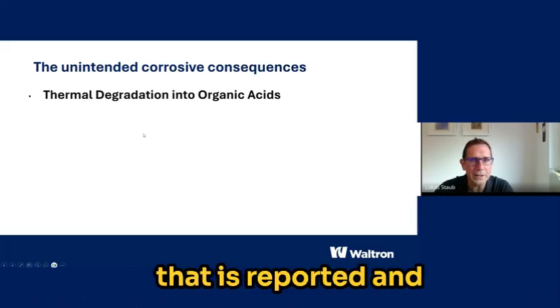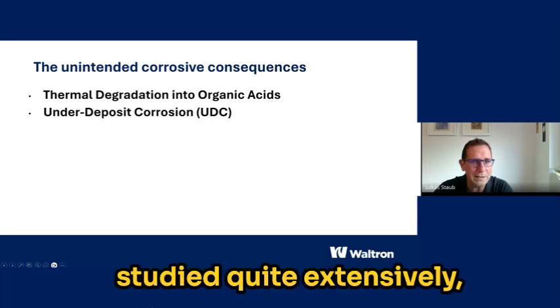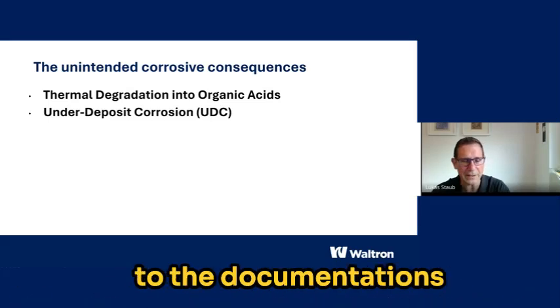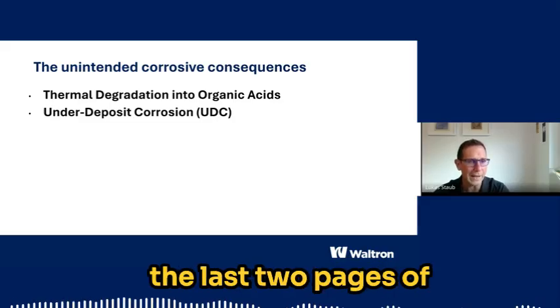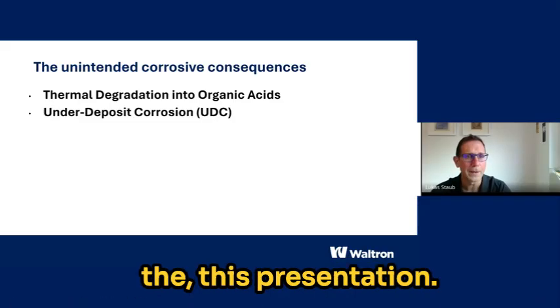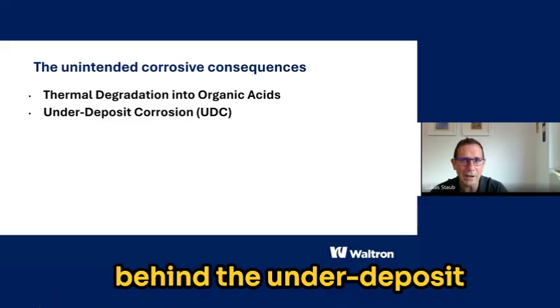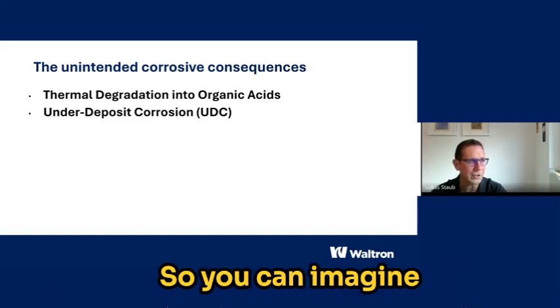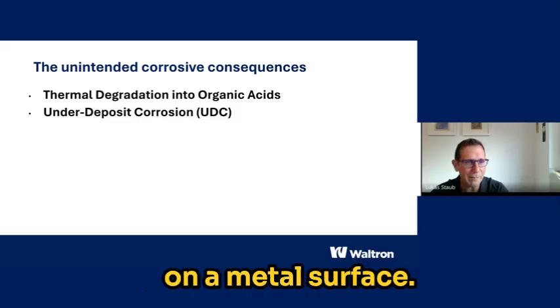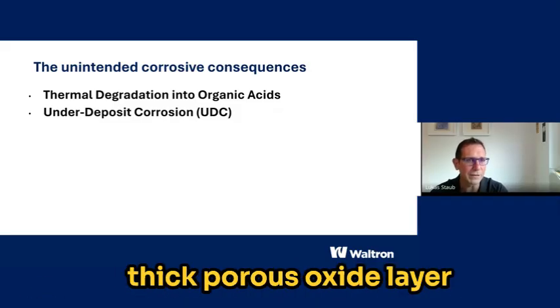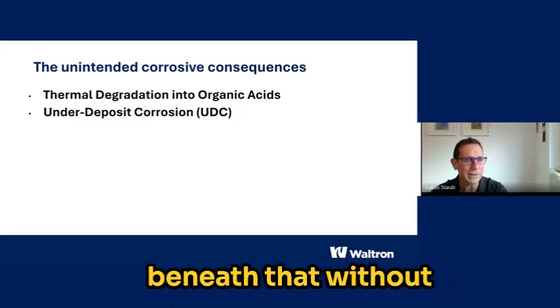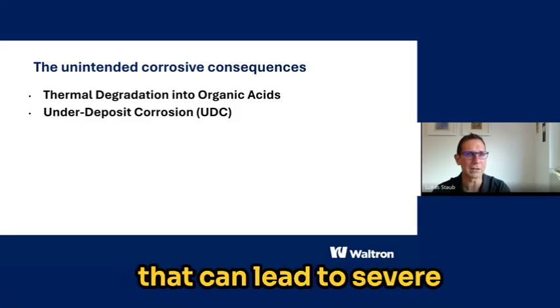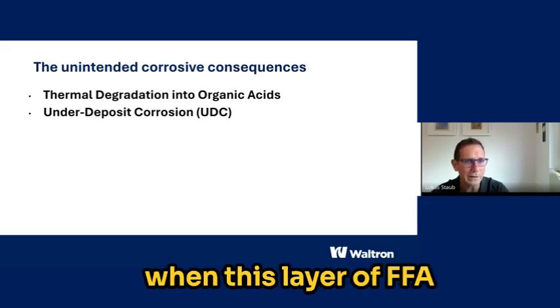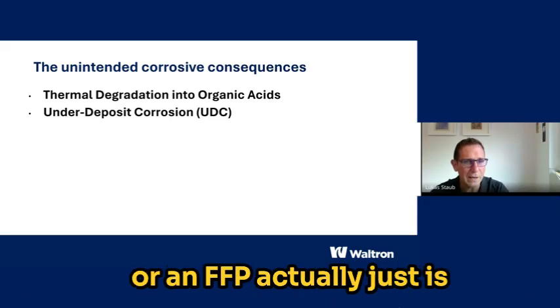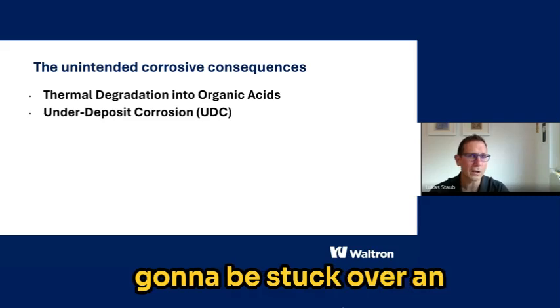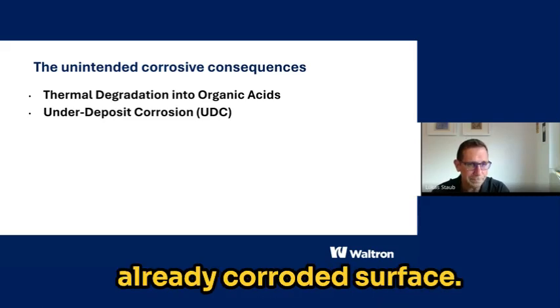Another phenomenon that is reported and studied quite extensively, and again, I'm going to refer to the documentation that I have listed on the last 2 pages of this presentation, is under-deposit corrosion. There is a lot of science behind it. So you can imagine this layer of FFA being on a metal surface. If you have, for example, a thick porous oxide layer beneath that without prior chemical cleaning, that can lead to severe under-deposit corrosion when this layer of FFA or an FFP is just going to be stuck over an already corroded surface.